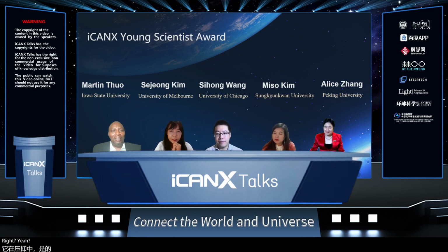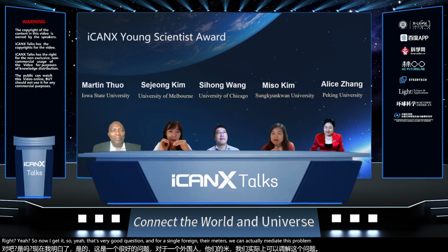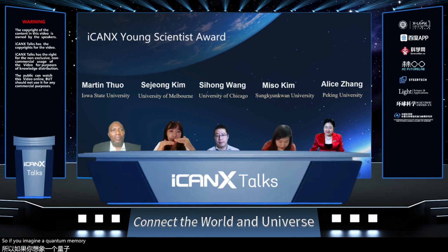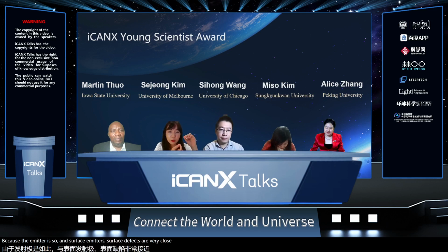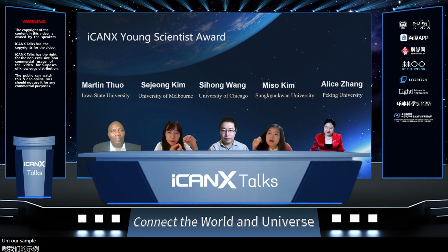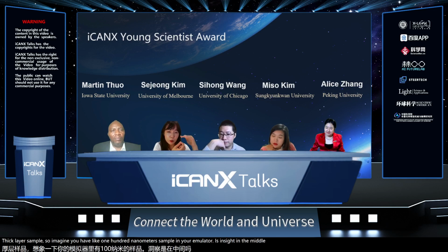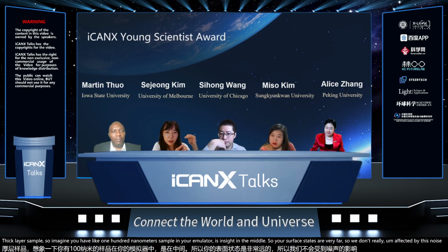Right. Yeah, so now I get it. That's a very good question. And for single photon emitters, we can actually mitigate this problem. If you imagine a quantum emitter in monolayer hBN, or a few-layer sample, then we have problems from the surface states and surface defects, because the emitter itself and the surface defects are very close. So our sample can be damaged by these signals. But the advantage of using hBN is we can use a thick layer sample. So imagine you have a 100 nanometer sample and your emitter is inside, in the middle. So your surface states are very far, and we are not really affected by this noise. Okay. So that's one thing for quantum emitters.